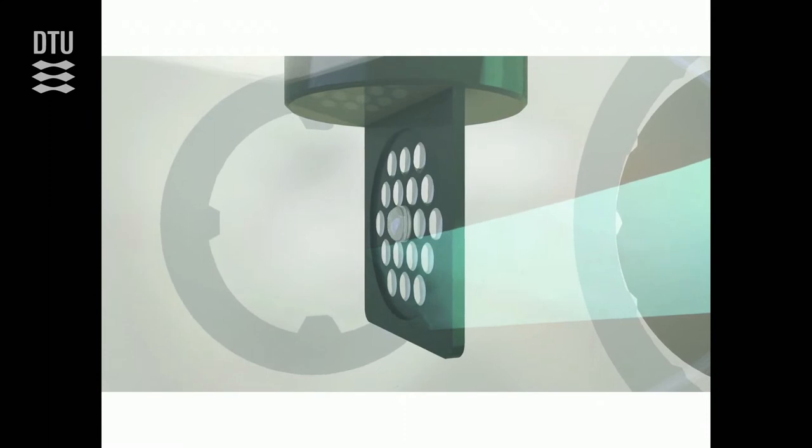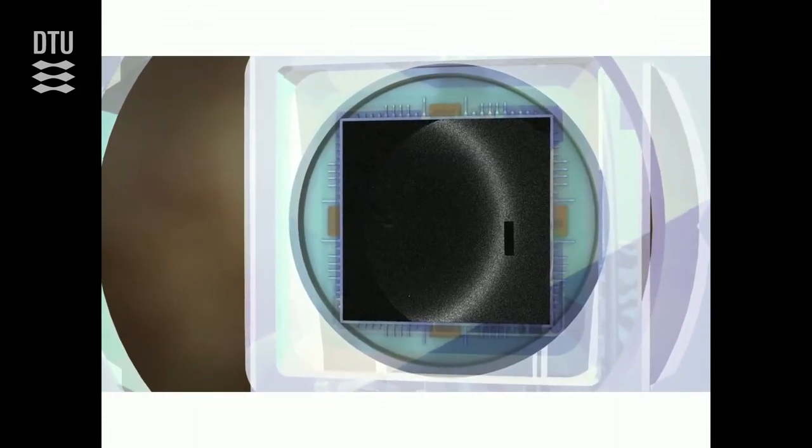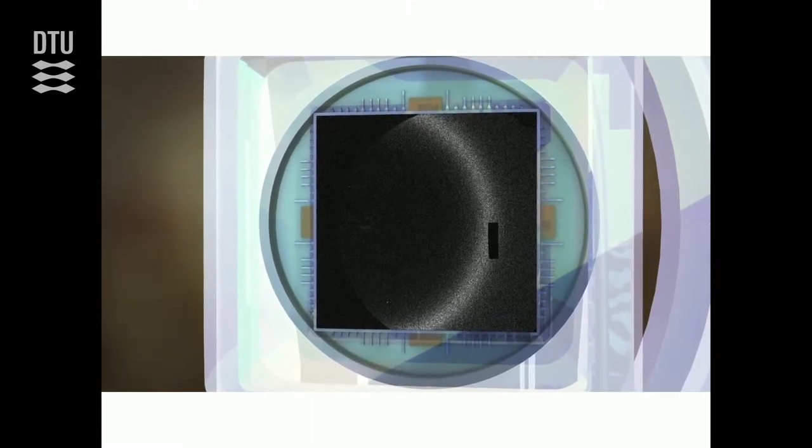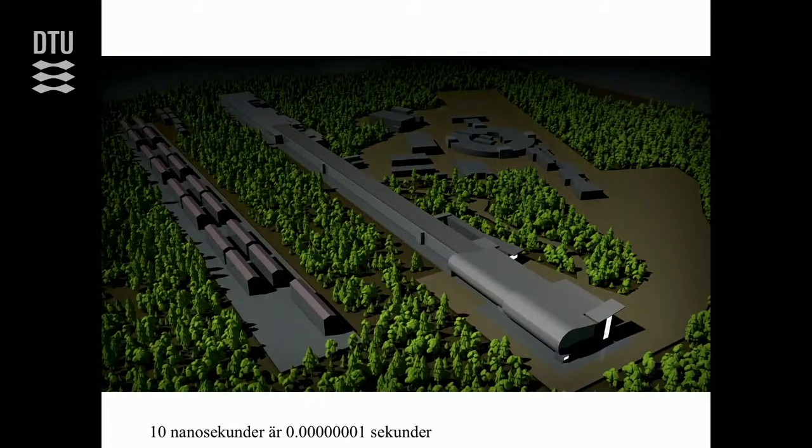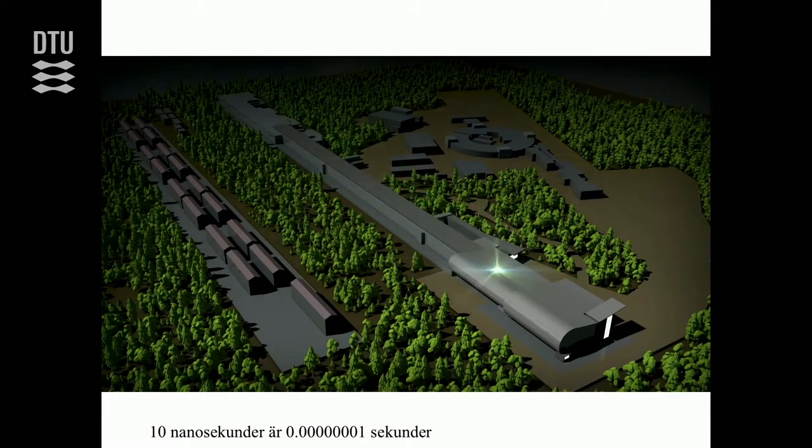And then we can come in with the different X-ray pulses, and we can look, will we see one ring like this? And if that ring, after we heat it up, just changes its position a little bit, will it indicate that we only have one liquid phase that expands, so to speak? If we see a lot of dots on the screen here, that would be an indication that there are no liquid phases up there, there is only ice. We are crystallizing the sample very, very quickly. If, on the other hand, we see two rings, it means that we have two different liquid phases present here.